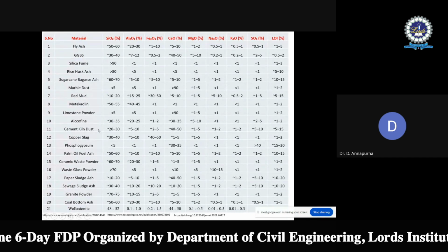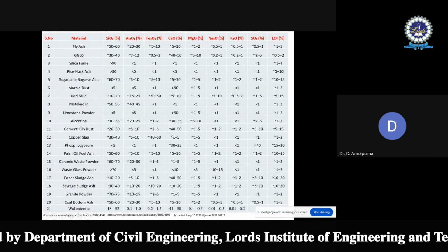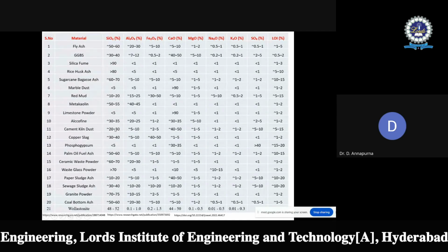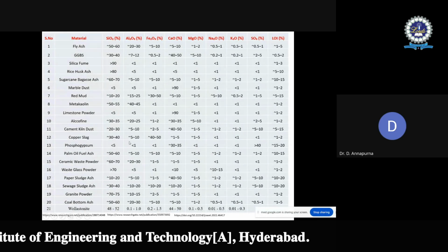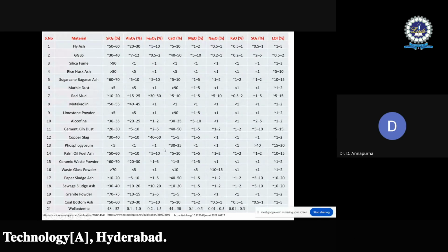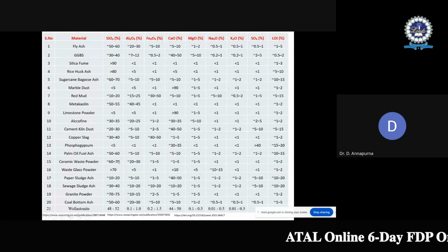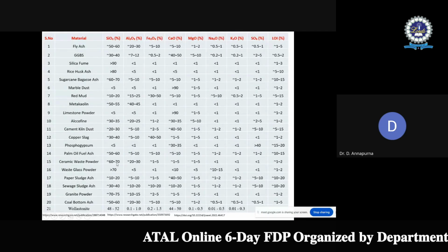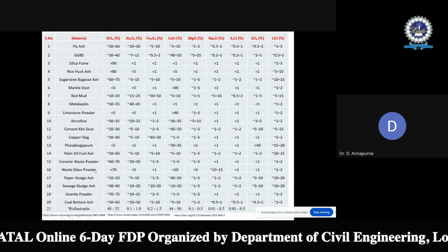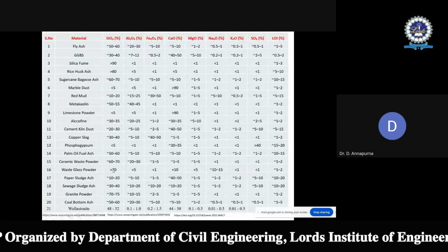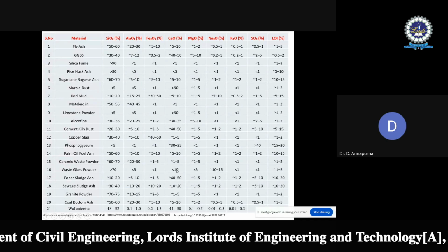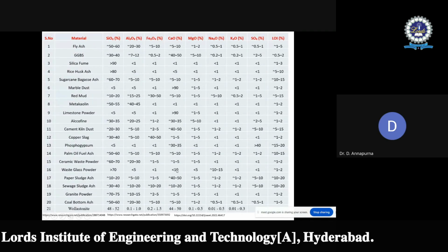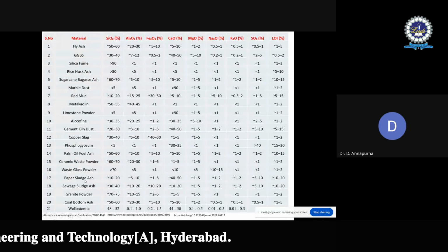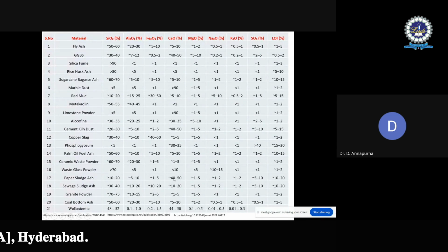Then cement kiln dust is a rich source of calcium oxide. At the same time, silica and alumina are also there. And then phosphogypsum, again 30 to 35%, like that palm oil fuel ash. Ceramic waste powder is rich in silica and alumina. Then ceramic waste glass powder is also rich in silica. At the same time, the calcium content will be less than 10%. Then paper sludge ash is also a rich source of calcium oxide.